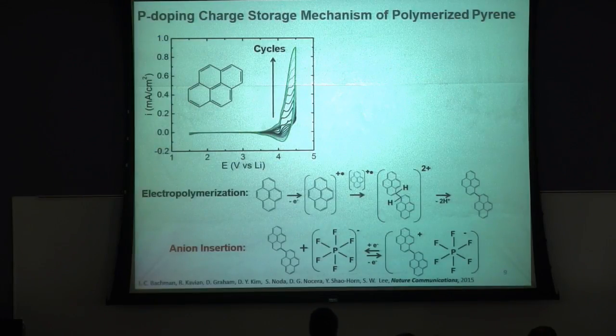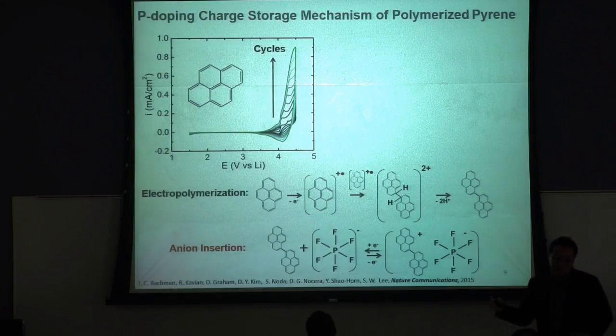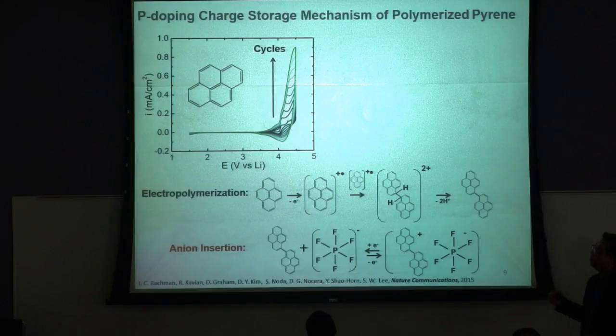So here is one example of a p-doping conducting polymer. This is pyrene. Basically, this kind of pyrene material is readily available during the fractional distillation process of crude oil or coal tar. If we dissolve this pyrene in an organic solvent and apply charge, we can remove 1 electron, right? So applying potential, removing 1 electron, we can create this kind of cation radical. Then this cation radical couples with another one and can generate this dimer. If we repeat this, we can create a pyrene polymer on the substrate.